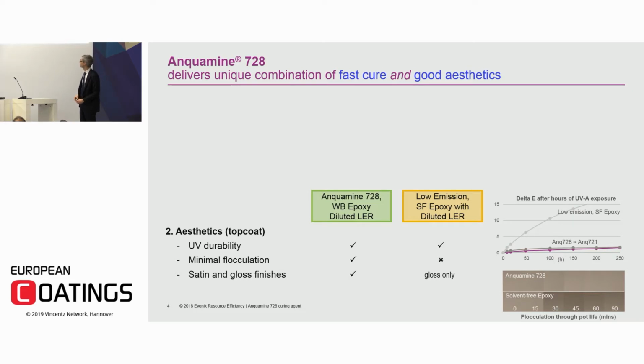And finally, it's very well known that with solvent-free systems, you can only get high gloss systems. So typically, customers do apply another coat to reduce the gloss, to get a satin finish. And with a waterborne system, it's actually quite an easy thing to do to get your satin finish in the same second coat.